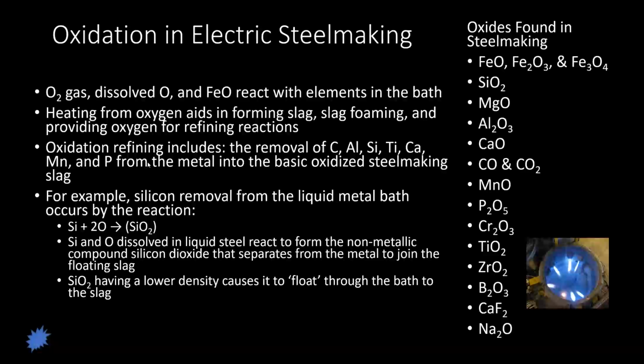So oxygen helps aid in foaming slag. It helps us along our process in the electric arc furnace. So when we're looking at oxidation in the electric arc furnace, we're looking at removing carbon, aluminum, silicon, titanium, calcium, manganese, phosphorus - all of these things in the bath.